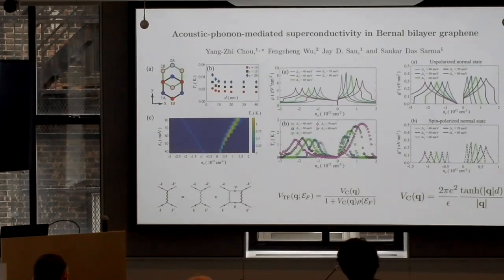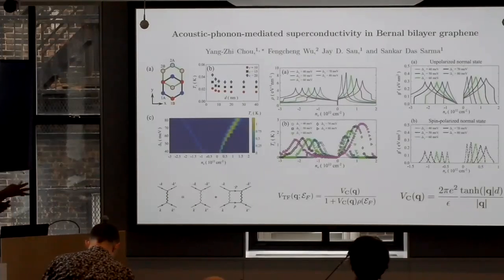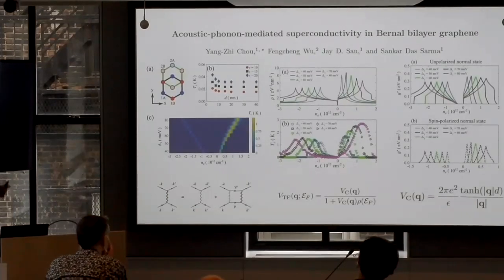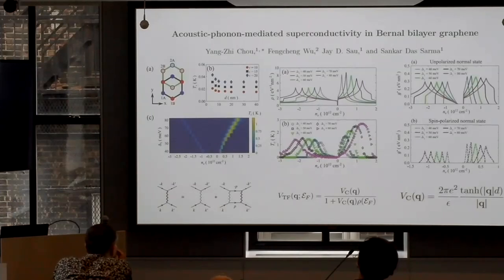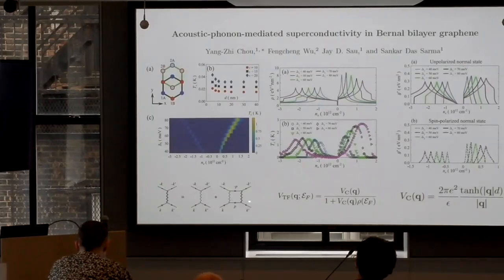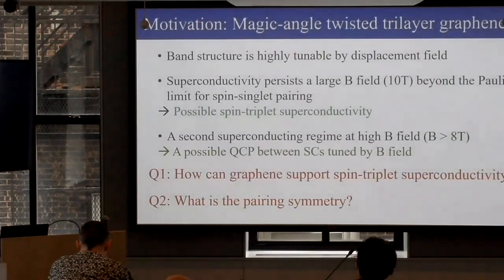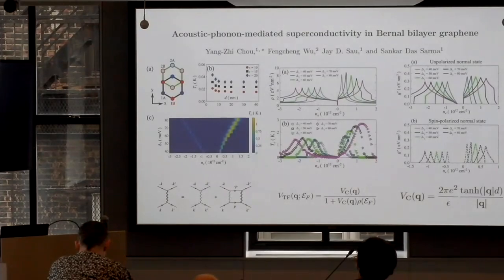Only thing, within our electron-phonon interaction model, and maybe if one does Hubbard model type calculation that Andy was alluding to, that I certainly was not familiar with, maybe the two systems will have very different Tc directly. But within our model, the only thing I could think of is that the mu star effect is very strong. So I said we have to include screening by the carriers themselves, and that we know how to do within ladder approximation. So we did that. And amazingly, Tc did go down to almost the experimental values. After including the mu star effect, we get results which are, not quite, but close to it.